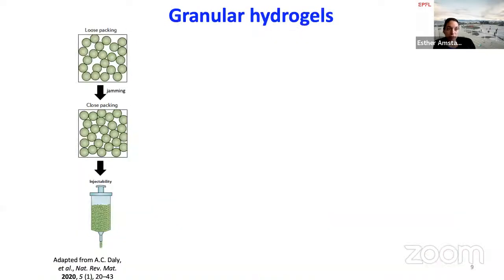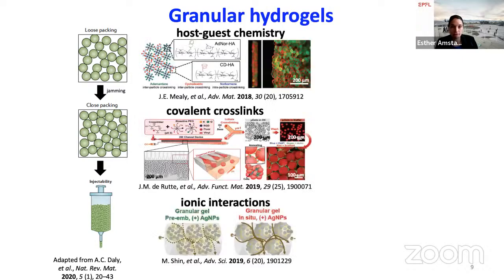And to me, a bit surprisingly, this concept has only been introduced into soft materials in a consistent way about 5 years back, where microparticles made out of hydrogels have been up-concentrated and then 3D printed into granular materials. And these granular materials are increasingly often used for tissue engineering because they have a quite well-defined porosity that allows exchanges of nutrients, maybe even cell penetration into these systems.